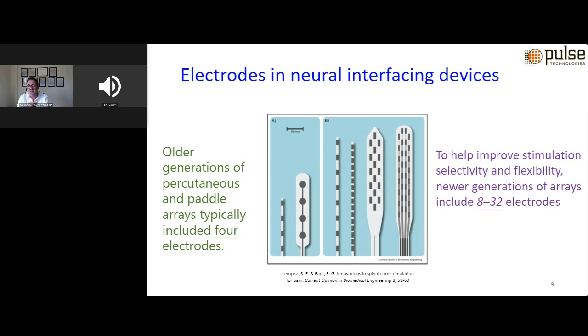When you look at the older generations of, for example, percutaneous and paddle leads and paddle arrays, they typically included 4 electrodes, for example, but with larger geometric surface area. However, as device manufacturers are shifting towards devices with improved stimulation efficacy, selectivity and also flexibility, the newer generations of electrode arrays are made with a much larger number of electrodes, oftentimes up to 8, 16, and even 32. But because of the limited space in the body, such as brain or spine, once the number of electrodes is increased for efficacy and selectivity, then the geometric surface area of the electrodes should decrease, but reducing the size of the electrodes actually leads to lower electrochemical performance.